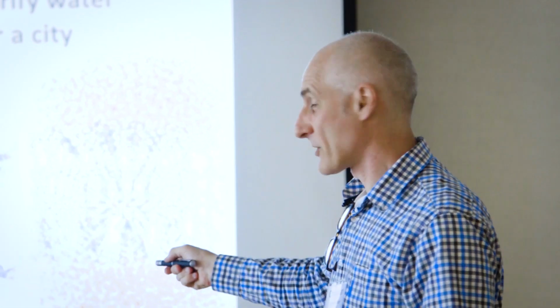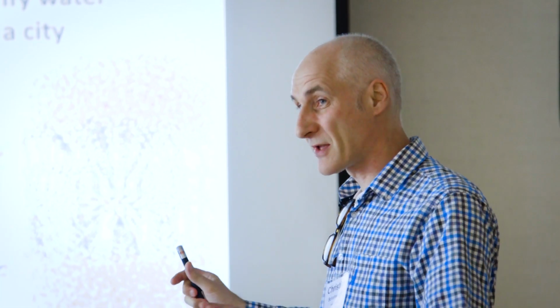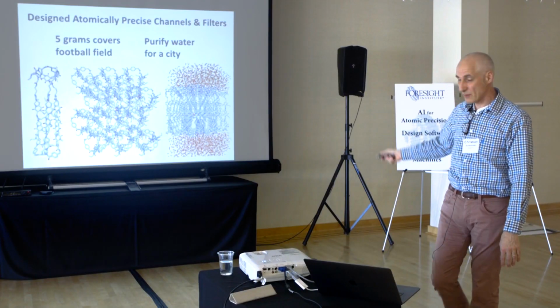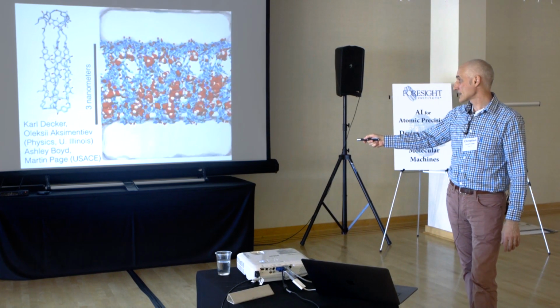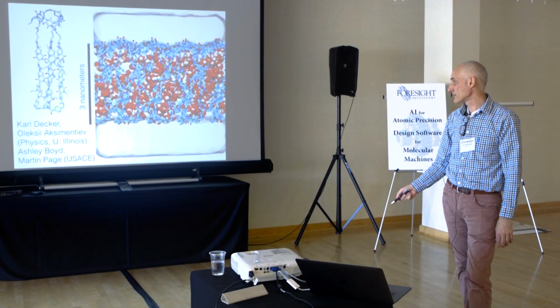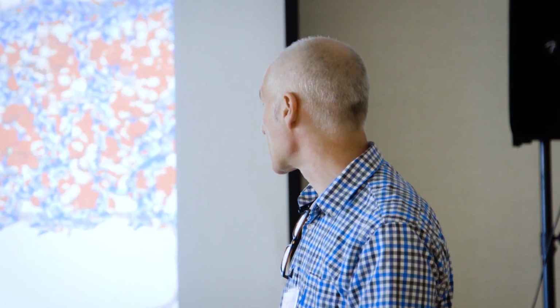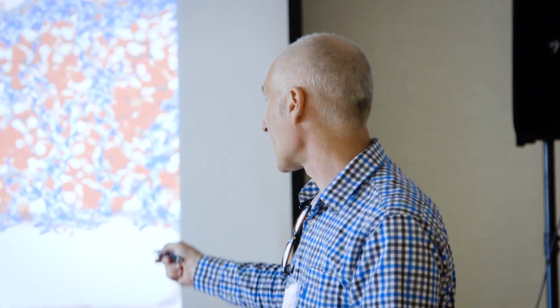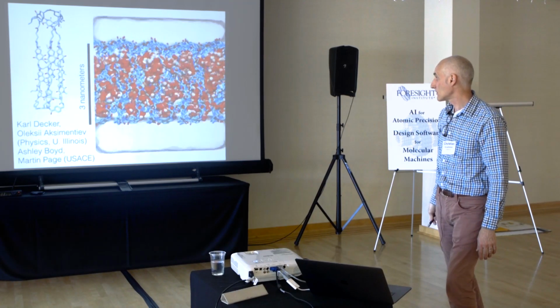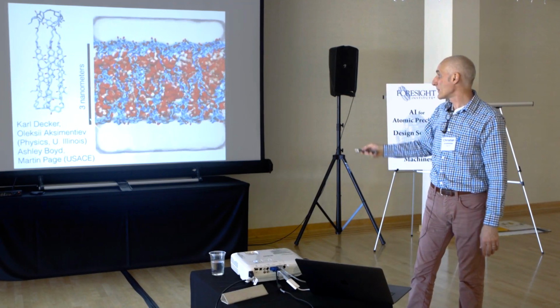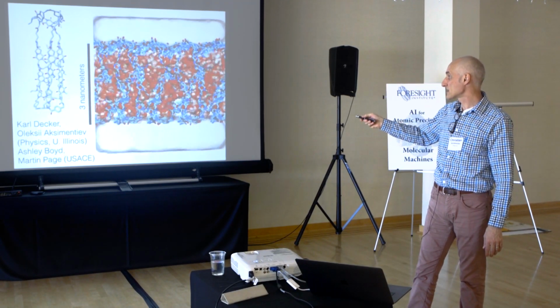And with the software that I've developed, I can build these molecules very quickly, build a two-dimensional network of them, pop them into a box of water on the top and the bottom, and then with the Tajkhorshid group at University of Illinois, they run dynamic simulations on these with NAMD, and we can calculate the flux through this membrane. It's about the thickness of a cell membrane. And then we can mutate the internal structure and then see how it changes the flux and computationally design molecules